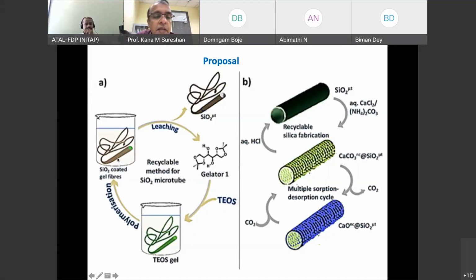And after some time, if you put in a little bit of amine, or even just water is also fine, this tetraethoxysilane will start hydrolyzing and it will nucleate silica around this fibrous particle. You know the mechanism of gelation, right? It will form the fibers. So around the fibers, it will form silica. And after some time, you can leach away, wash away this gelator. What you have is a hollow cylinder of silica.